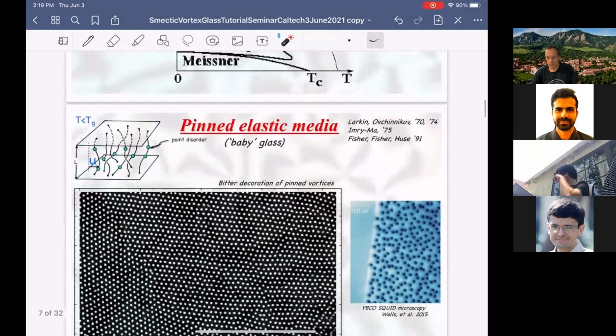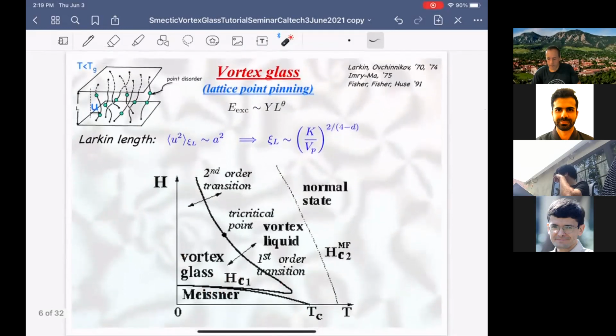So the phase diagram that you have is above a certain disorder strength? No, that's the thing. For arbitrarily weak disorder, because this thing diverges with system size, in 3 dimensions, and the upper critical, or I could call it lower critical dimension 4, it's just an instability of the XY model in a random field. That's really what it comes down to in terms of a calculation, with only some bells and whistles to account for vortex physics. But it's really just a random field XY model in 3 dimensions or below 4 dimensions.